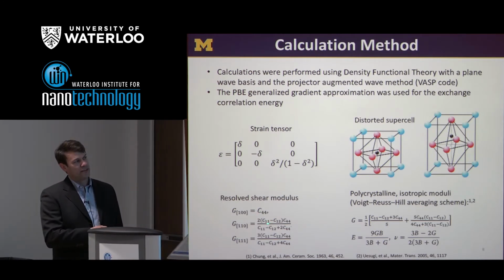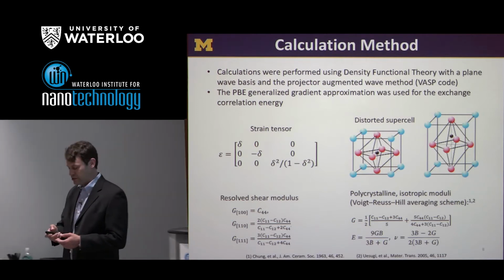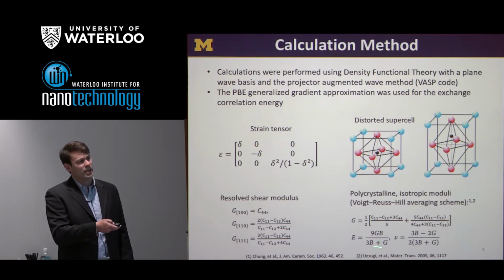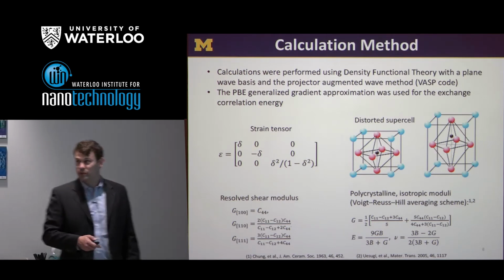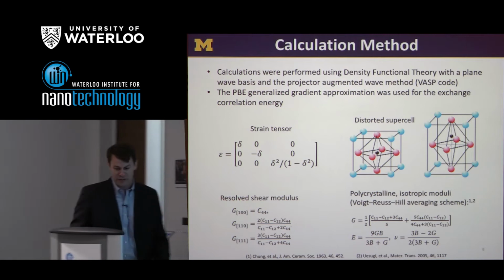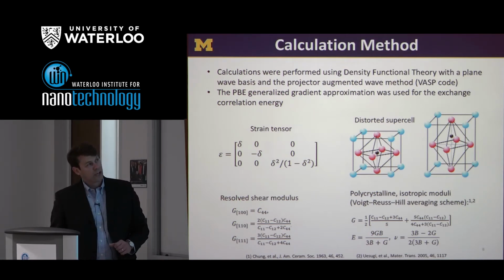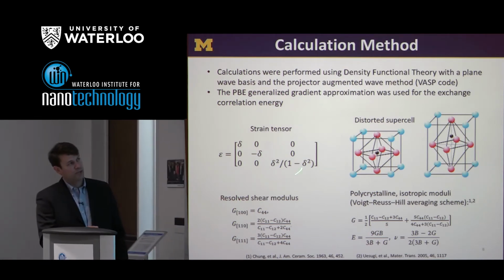And by evaluating these, we can combine them in different ways using these averaging schemes to get, for example, the polycrystalline isotropic shear moduli, which is the main thing we want to get out of this calculation and compare with that of lithium, but also Young's modulus, the Poisson's ratio, and these moduli can also be resolved into different crystallographic directions. And the way this works is that we basically develop a strain tensor or some method for straining the crystal, and this is shown here on the right with a cartoon.